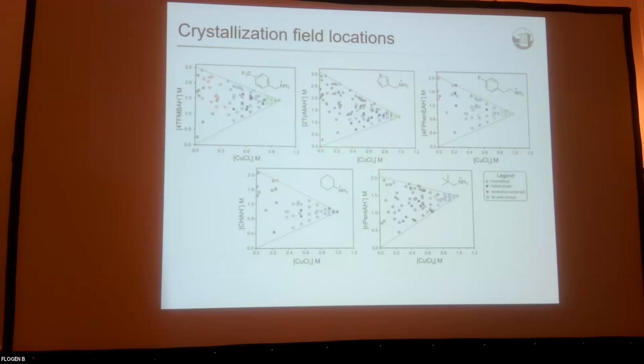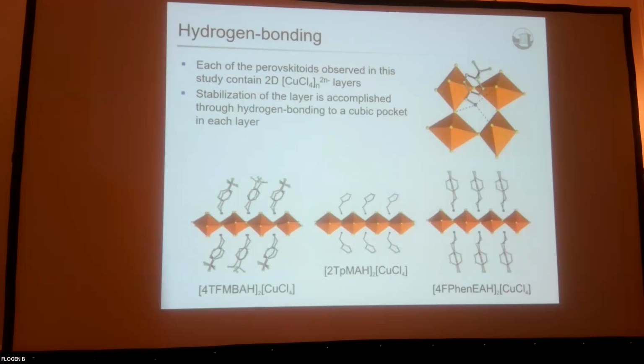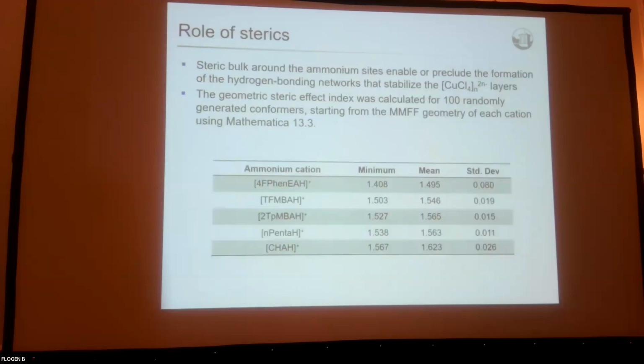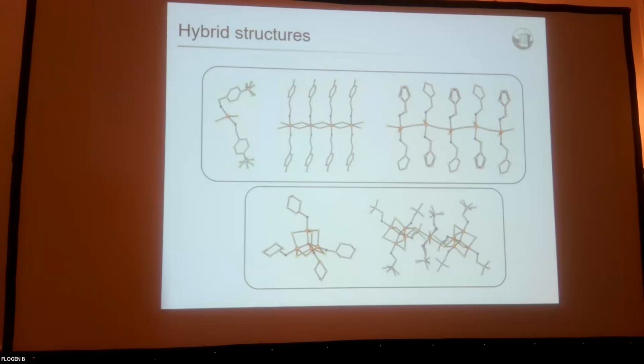In order to think about that, we had to look at the packing structures of these materials. And if we look, what we see is that hydrogen bonding is, again, important. And with this hydrogen bonding, there's a primary ammonium site that's in a cubic pocket in each of these materials. And the ability of these amines to occupy these cubic pockets is based upon sterics. And so we calculated some geometric steric effect indices, and we see that the sterically less hindered ammonium sites can result in stabilization through hydrogen bonding in cubic pockets and result in the formation of perovskitoid. The sterically more hindered amines can't. If we look at the structure of the hybrids, sterics also affect that as well.